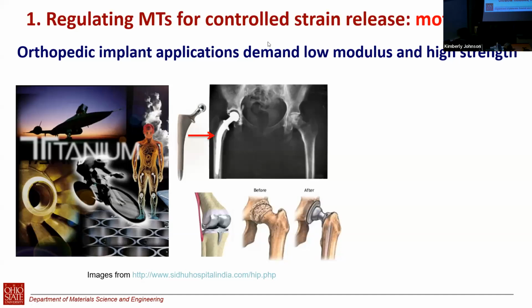So the idea is, if you can create a concentration modulation in your materials in bulk form, locally you can have some materials where the martensite is already stable at this temperature, and the others gradually change the stability. For some of the materials, you have to go to very low temperature in order to transform into martensite. Very difficult to transform. The same thing for the applied stress.